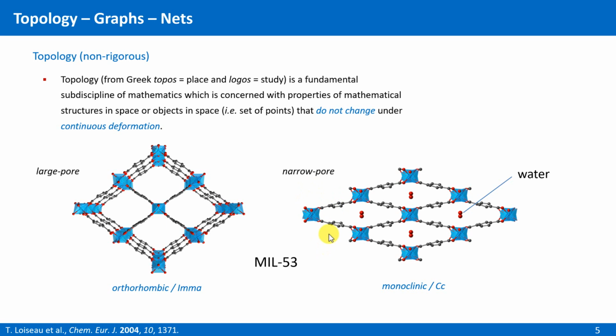Okay, during this phase transition, almost everything changed: the fractional coordinates, the symmetry, the space group, everything that is characteristic for a crystal structure. But do you really consider these two variants as fundamentally different? Well, from a topological point of view, they are identical. Why? Because they can be continuously transformed into each other. And here continuously means without breaking or reconnecting any bonds. And this is exactly the link, the relation to topology.